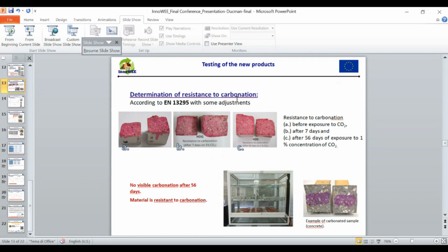So the first one we have tested is carbonation, because this is important if steel reinforcement is incorporated in such material. If the material is not resistant to carbonation, then there is a fall in pH value after the carbonation process takes place, and this can accelerate corrosion. So we exposed our samples for 56 days to 1% of CO2 and measured with indicators if there is any drop in pH value. There was no change, so in our case, geopolymer panels are fully resistant to carbonation. Here you can see an example of how it looks in concrete samples if they are not resistant to carbonation.